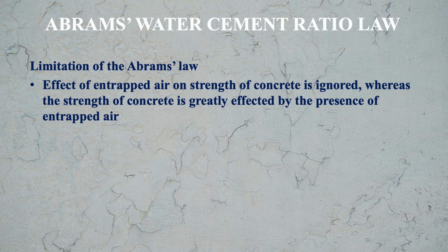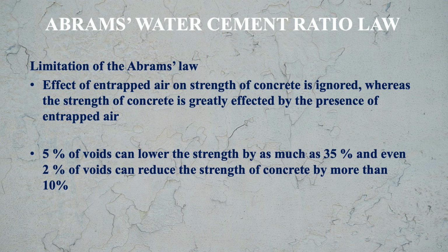What are the limitations of Abrams' law? Let us see. Effect of entrapped air on strength of concrete is ignored in this law. Whereas the strength of concrete is greatly affected by the presence of entrapped air. And how is it affected? 5% of voids can lower the strength by as much as 35%, and even 2% of voids can reduce the strength of concrete by more than 10%. So that way a small amount of voids also has a great effect on the strength of the concrete.